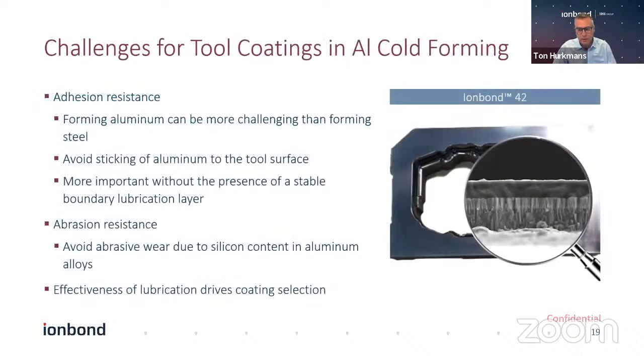You see here an example of a coated die on the right-hand side and the magnification of a coating architecture that was deposited by PVD. The coating thickness is around 5 micrometers in total, just to give you a feel for how thin these coatings actually are. That is also good because they don't change the tolerances of a very nicely designed die. The die tolerances will be maybe 0.05 of a millimeter, but we are certainly an order of magnitude lower in our coating thickness.